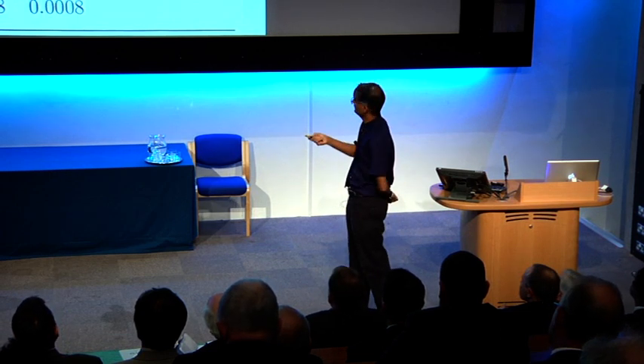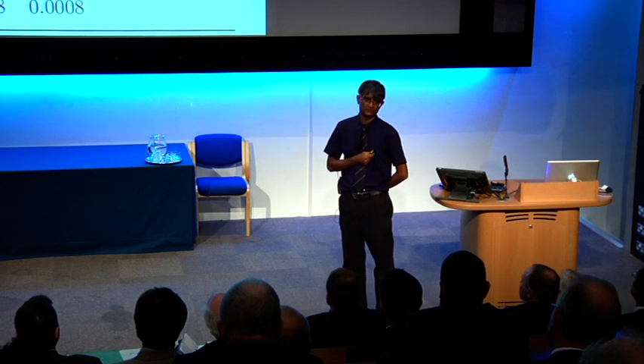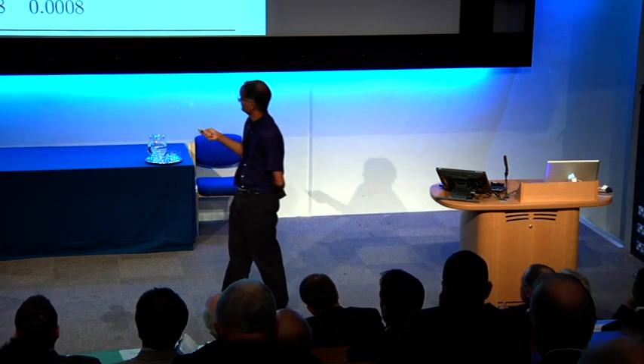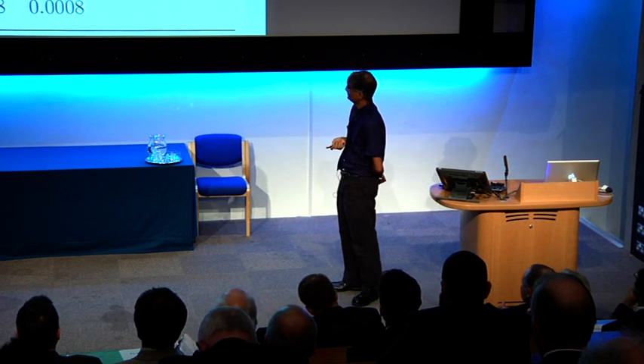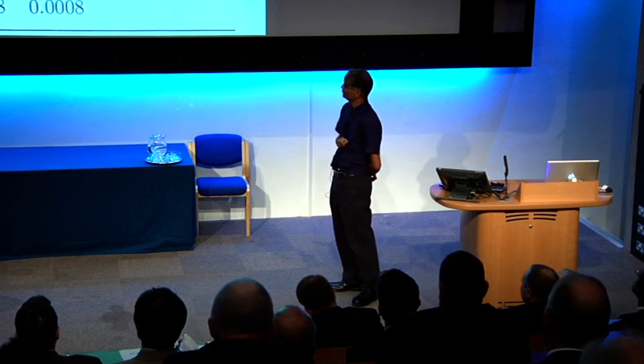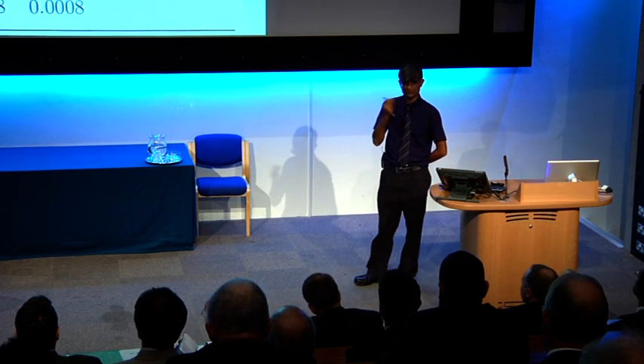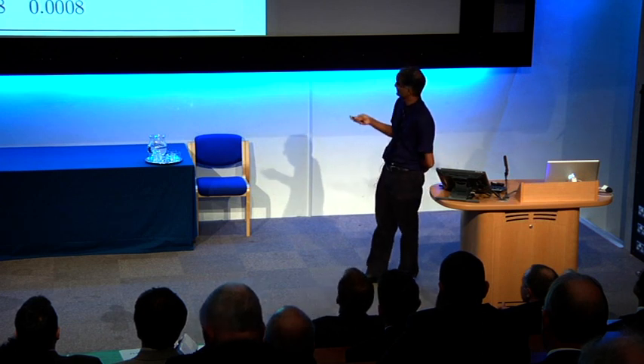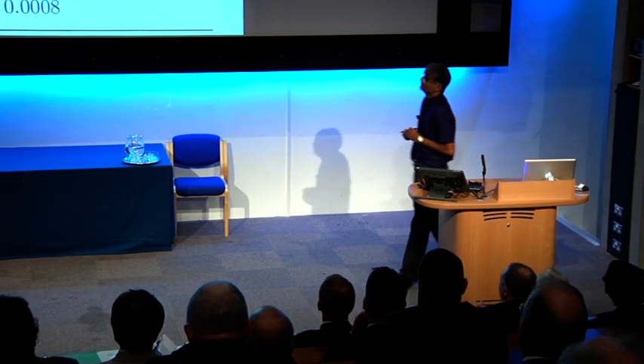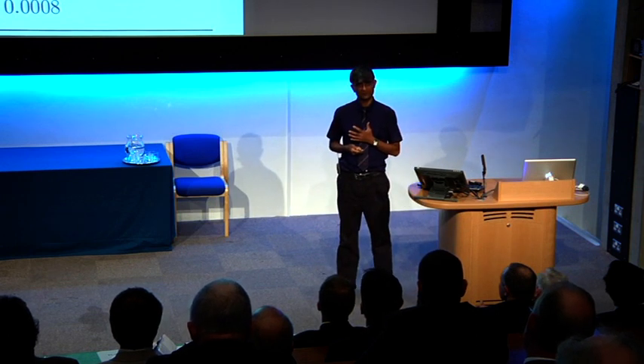And the improvements over the last 4 decades or so have really been in this area. These are very, very small concentrations of elements that will exist in the steel, even if you don't put them in. So sulfur, for example, is between 0.003 and 0.023 weight percent. Keep this number in your mind, about 0.015 of phosphorus, nasty element to have in a steel. Oxygen concentrations are 6 parts per million in modern bearing steels. Just 6 parts per million. So by cleaning the material up, the performance that we've had from this particular alloy system has improved systematically over the last 4 decades.